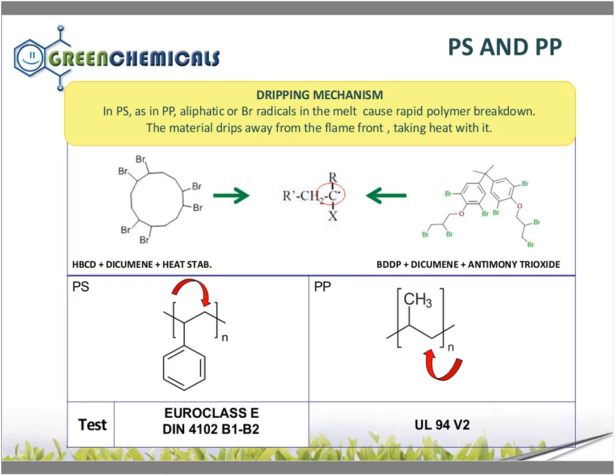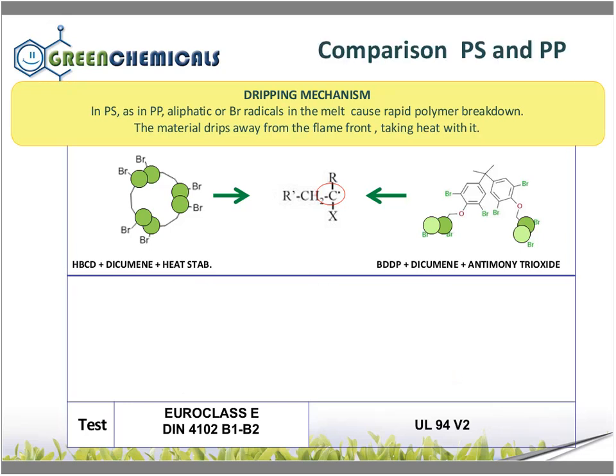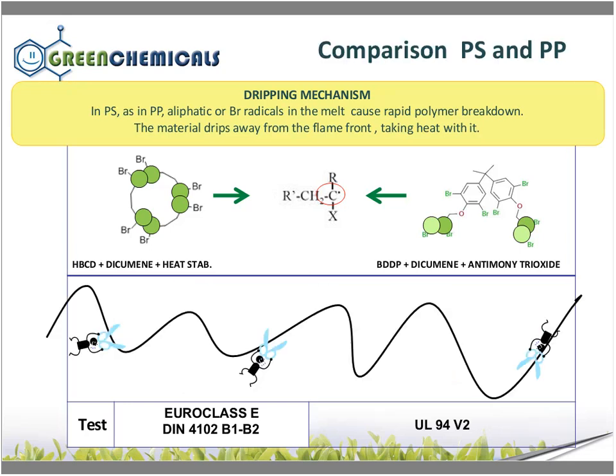These two are brominated compounds, and these are very good initiators because the bromine is bonded to a secondary carbon. Actually, what happens is that the aliphatic brominated radicals in the melt will cause this dripping, this polymer breakdown. The material drips away and it takes the heat away from the flame front. If you look at these two molecules, you will see that the active sites in the HBCD are much more than in the BDDP. This is just to let you understand why HBCD is so active in polystyrene. You should imagine these polymers like a long chain, and the radicals will cut this chain into smaller pieces, causing the breaking that we observe.